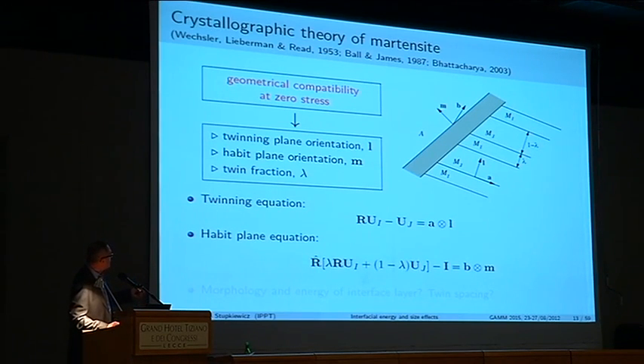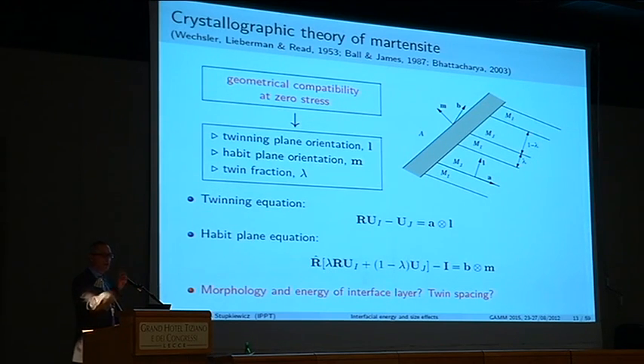And there are equations which express compatibility of deformation gradients in individual phases, in principle rank one connectivity of deformation gradients. It doesn't matter. We know how to write these equations. We also know how to solve them. So starting from this geometrical compatibility, we can obtain all the microstructural parameters of this microstructure, orientation of interfaces, volume fraction of twins, etc. What you cannot do, you cannot say anything about what's in this gray layer here, symbolically denoted. The transition layer is unknown. We don't know what is the microstructure. We don't know what are the characteristic dimensions, the twin spacing in that case. The theory does not say anything about that.